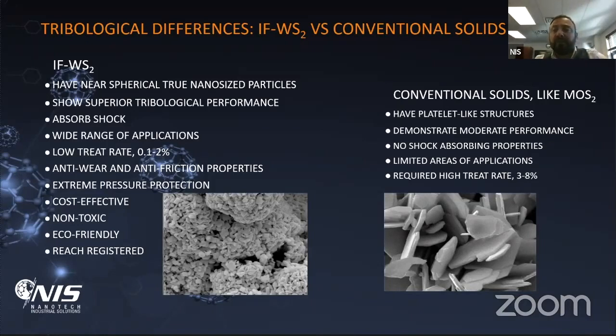With molybdenum disulfide, because of the platelet type of structure, they demonstrate moderate performance in tribology. Before IF-WS2 was known, for example like 25 years ago, it was one of the best solid lubricants. Right now, we increase the standard. They have no shock absorbing properties because they transfer the shock and don't really protect from micropitting. They are used in heavy load and low speed applications primarily, and they really require very high treat rates. Usually lubricants, and primarily greases, as I mentioned, have between 3 to 8% of molybdenum disulfide.